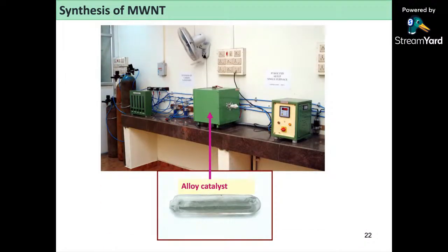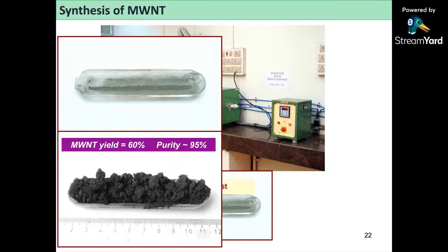And this is the quartz tube, and then inside, you kept the quartz boat, and these are the gas manifolds. So one can get the carbon nanotubes after half an hour. You can see this is a catalyst that we used, and this is the carbon nanotubes that have been grown on top of the catalyst.